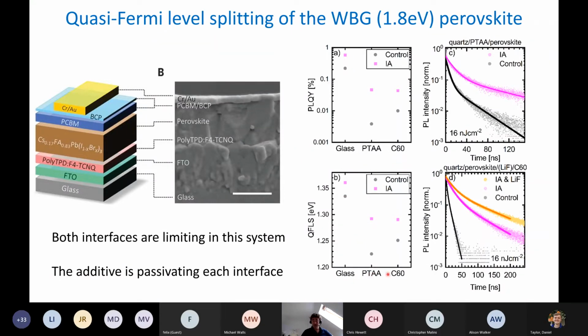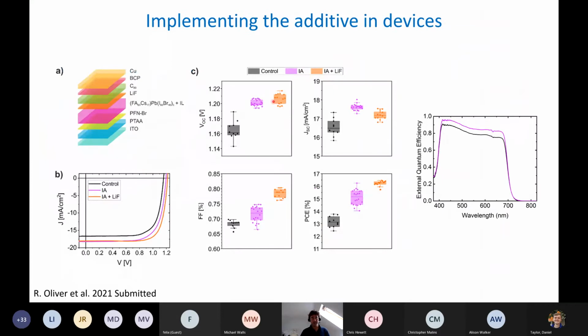If we look at when we put the different contact materials on, we find this voltage is reduced. So we're getting more losses at the interface between the perovskite and the hole conductor, and C60 is the electron conductor here. We're also getting losses there. Notably, with the additive added, these losses are reduced. So these devices should give a 1.3 volts open circuit voltage. In reality, they improve, but they don't deliver 1.3 volts. They deliver about 1.2, 1.22 volts.